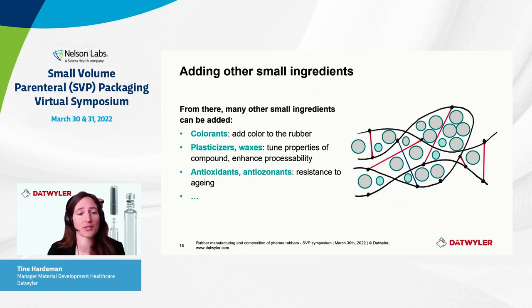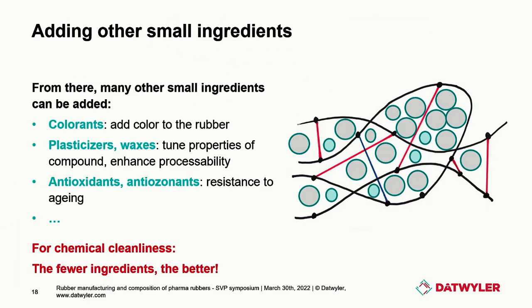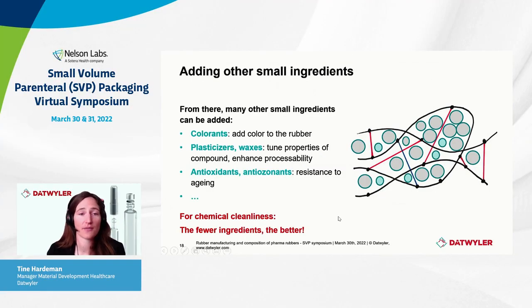And also, of course, other ingredients are possible. But in fact, for chemical cleanliness, the fewer ingredients, the better. Of course, you need to add enough ingredients to really get a rubber with nice properties that gives you all the properties that you need, in fact. But if you can do this with less ingredients rather than more, this will obviously be preferred because what you don't put in the rubber cannot come out of the rubber. So every ingredient that you add is another component that can give rise to new extractables. So we really try to work with as little ingredients as possible, but of course, taking into account that you need to have good rubber properties.